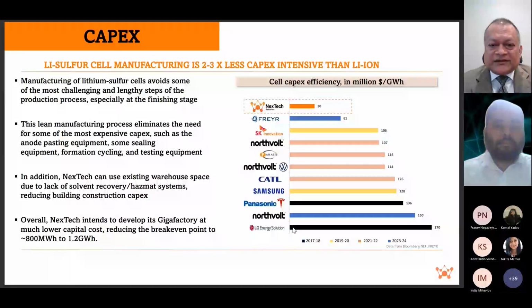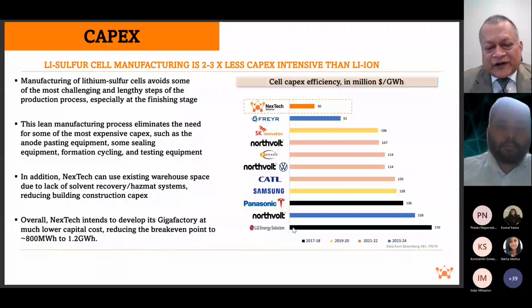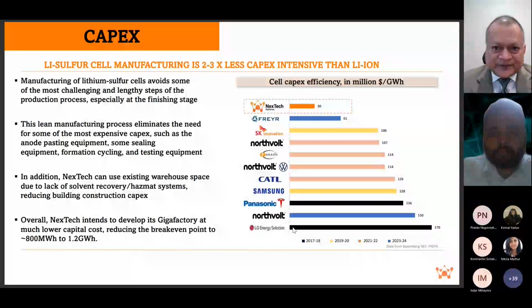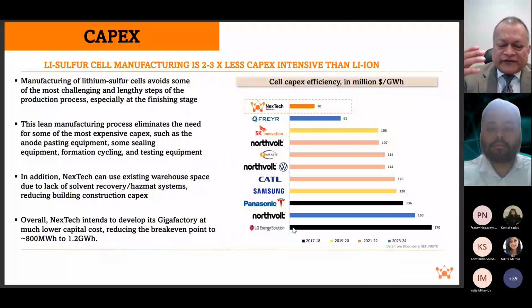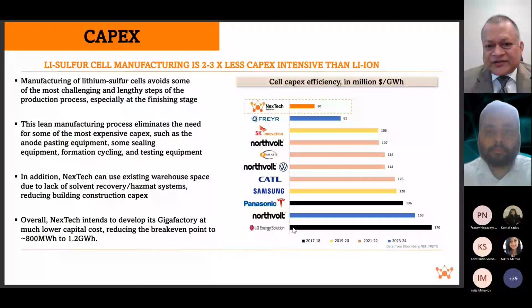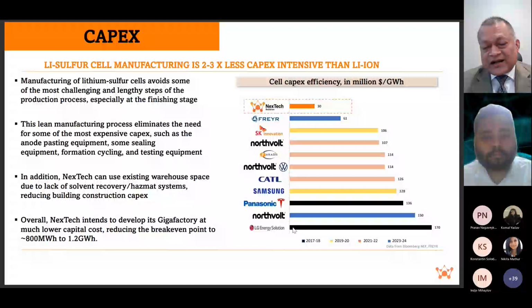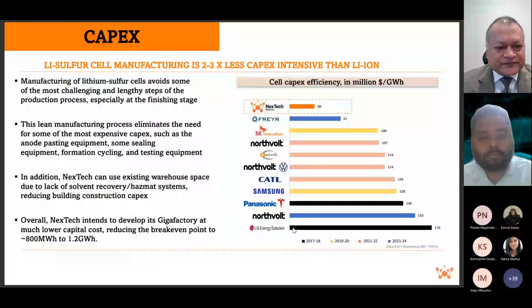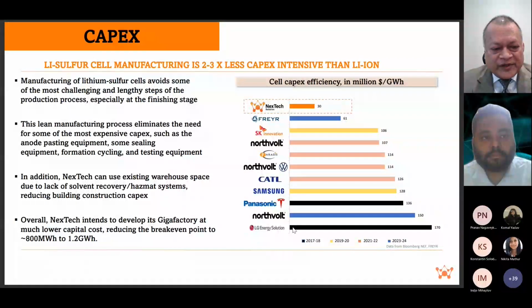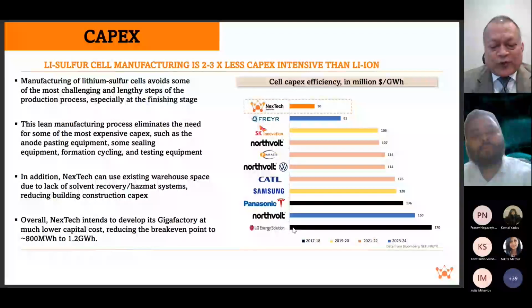So this number can be brought down even more if I were to redesign my pasting of cathode active material. So even though we are very low, the lowest of probably many of the technologies in terms of capex numbers, that number still can be brought down by another easily 15 to 20%. So the break-even point we believe is 800 megawatt hours to 1.2 gigawatt hours, depending on the location of the plant. That number is about half of what it is for traditional lithium-ion batteries. Next slide, please. Thank you.